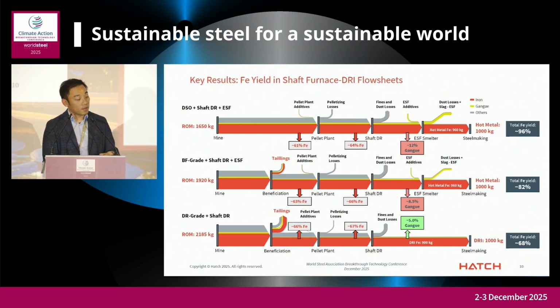And of course, on the bottom, instead of 1.6 tons of iron ore per ton of DRI, you basically need about 2.2. And yield difference is not just an economic factor, but any yield loss is going to turn into either a solid waste, steelmaking slag, or something like that, or a tailing in beneficiation. So it's an impact that stretches across the cost and economic, as well as environmental waste generation aspects. So I think it's something worth highlighting. When I first did this analysis, I was quite surprised to find out how much of an impact there is on overall iron use when we start accounting the iron units from the moment it leaves the ground.